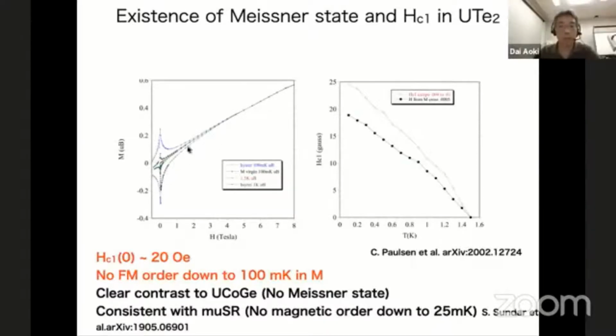Here you can see the nice magnetization curve. What is important is that uranium ditelluride has an HC1, a lower critical field, and this is about 20 Oersted. This is quite in contrast to the case of uranium cobalt germanium. In uranium cobalt germanium, because this is a ferromagnetic superconductor and it's always in the mixed state, there is no HC1. However, in uranium ditelluride, we could clearly see the HC1.